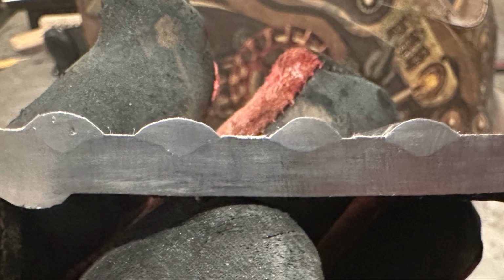And I think what happened was the thicker plate pulled the heat out of the weld so fast that essentially the escaping gas was trapped inside of the solidifying weld. Now the second pass without gas, even that has porosity.